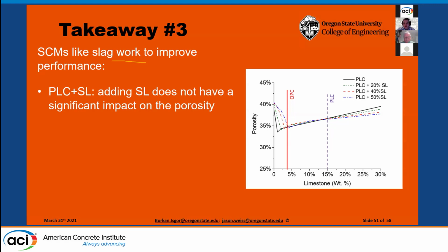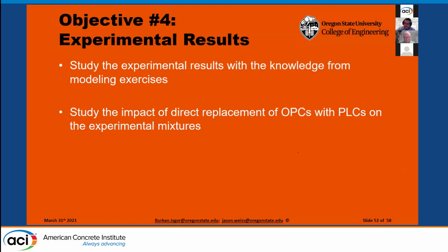It's actually starting to decrease the porosity in the system, but we don't see that huge benefit we saw with just straight alumina, partially because of the partial reaction and partially because of the fact that slag isn't 100% alumina. But what we see is a very similar type of porosity, but we do see some benefits when you get out to higher and higher values. We also see that the slag is stabilizing more of those phases because of the reaction with alumina in those systems.